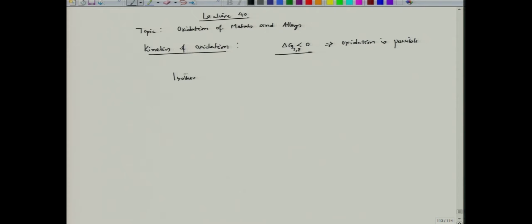So, when we talk about kinetics, it has been noticed that kinetic processes have different rate laws. The oxidation process can be linear, it can be parabolic, it can be logarithmic, it can be cubic, and those rate laws are specific to some metals. Of course, there are reasons for it, but at least we can find out whether this particular oxide formation is parabolic or not, or cubic or not, or something like that. In order to do that, we need to do experiments. There are two ways one can find out. One is isothermal, another one is non-isothermal. So, these are the two routes.